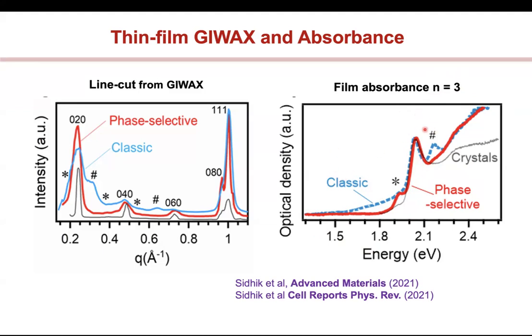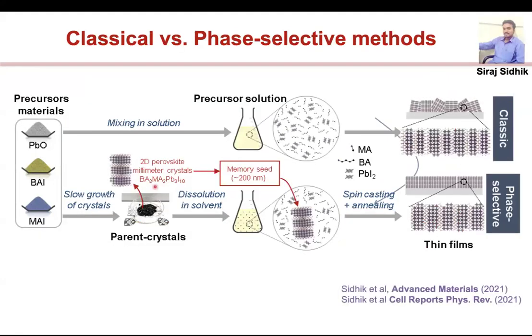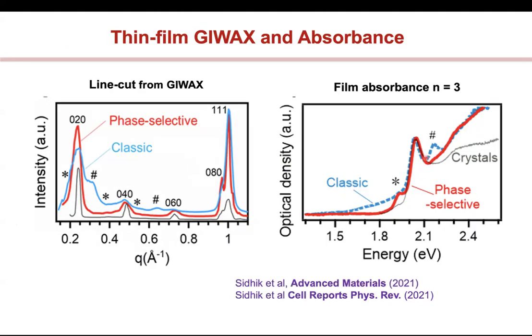Okay. So if I take this and do this, we were able to control and see that when I take these N3 crystals and dissolve them, I get a film that is phase selective, which means it's very selective to the N3. Similarly, if I do this using the classical method, which I showed you, which is this, then we were getting films that had mixtures. For example, look at this peak here, look at this impurity here, and then you can see this tail. And it extends all the way to that of a bulk or a 3D perovskite. And so we were getting these mixtures which were not very pure.